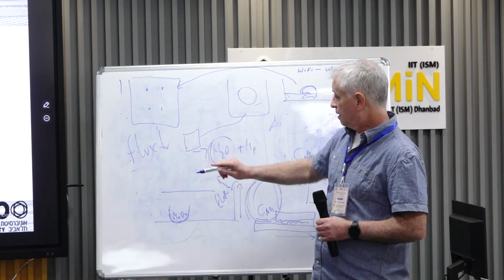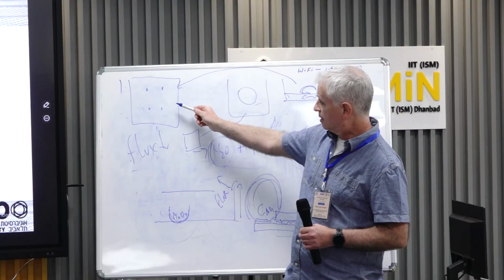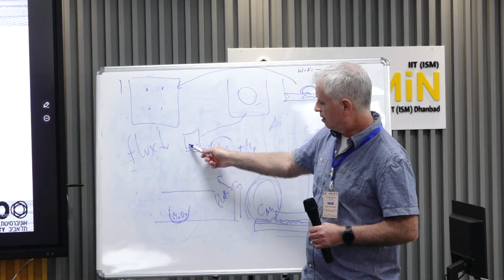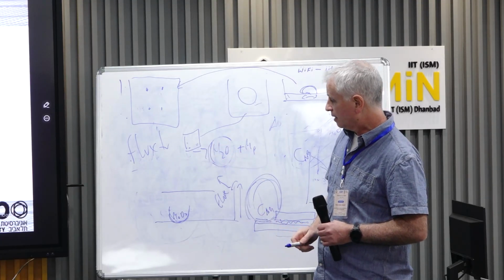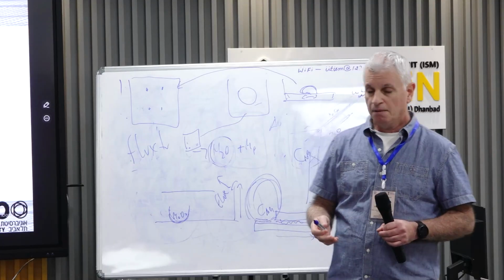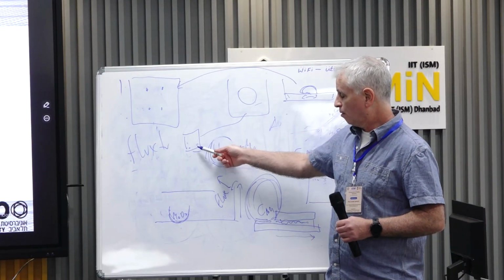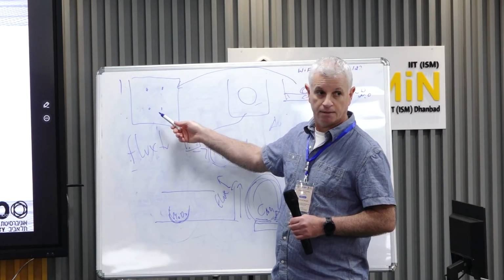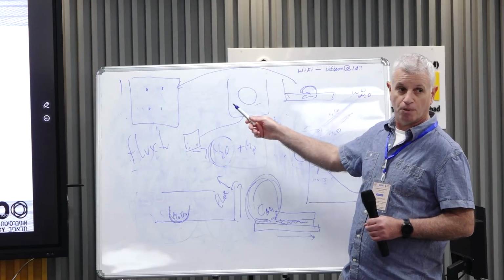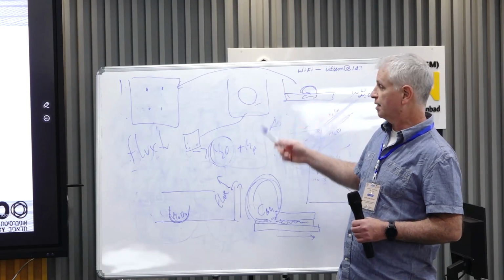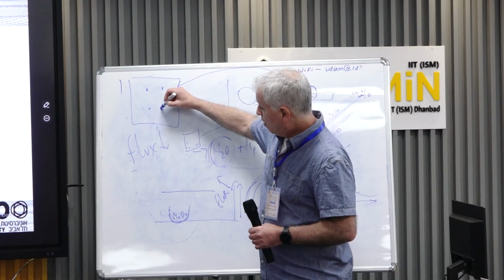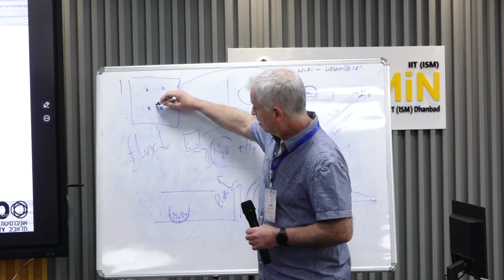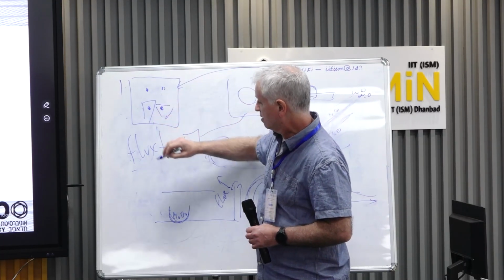When we grow like that, we don't want to grow on top of clean areas, because in general the stable nuclei on these areas need to be larger than the ones on these areas. That's the whole idea of homonucleation against heteronucleation. That's why we use seeds with different distances, and we can control the domain size.